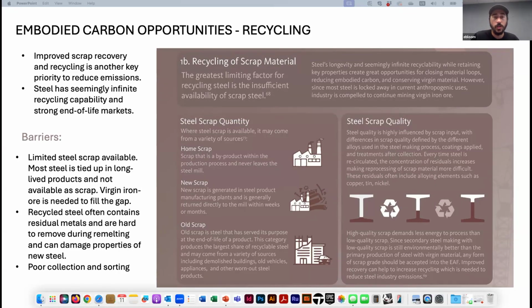Recycled steel also often contains residual contaminants such as chromium, nickel, copper, tin. These are harder to remove metallurgically when remelting, and so it makes reprocessing difficult each time it's recycled. And it can negatively affect the structural properties of the new steel. So I think recycling steel will become a key strategy moving forward for the steel industry, but it requires improved sorting and collection methods, particularly in other parts of the world where steel scrap might be going underutilized, or if it's happening at all.